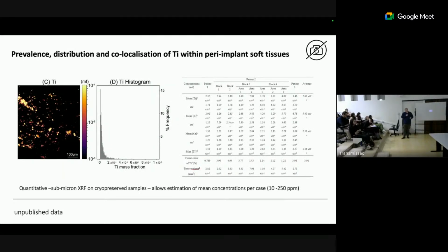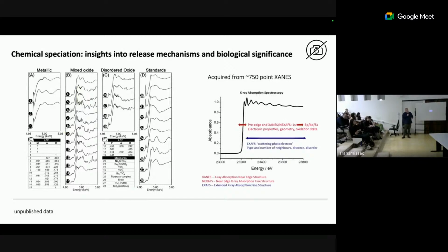So by doing this, and again, I said we've looked at nearly 25 individual patients with about 50, 60 specimens interrogated over this time. We've been able to understand what the mass fraction of titanium is, the size of the titanium, but the other thing that we should also be looking at is what chemical form is that material in. So that takes us to another technique, which is called X-ray absorption spectroscopy.